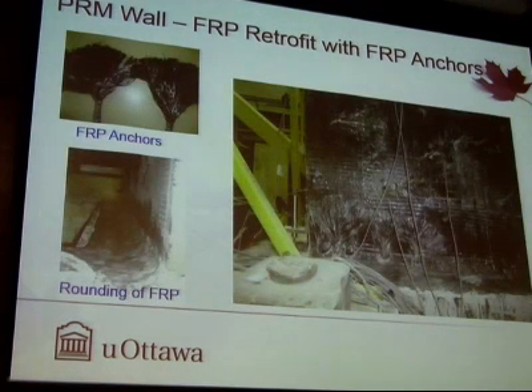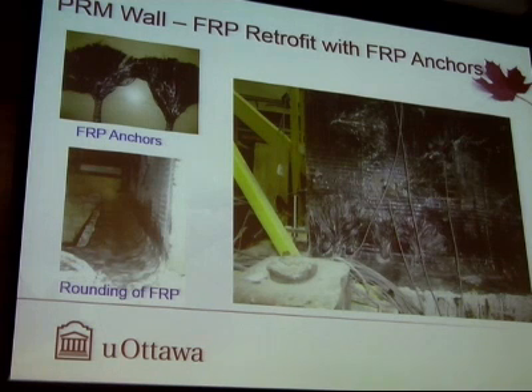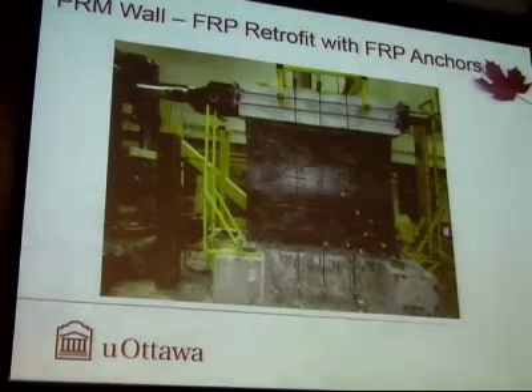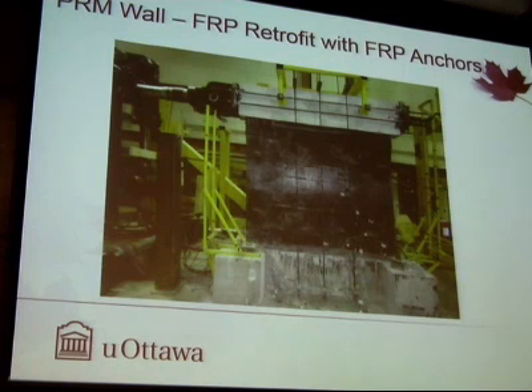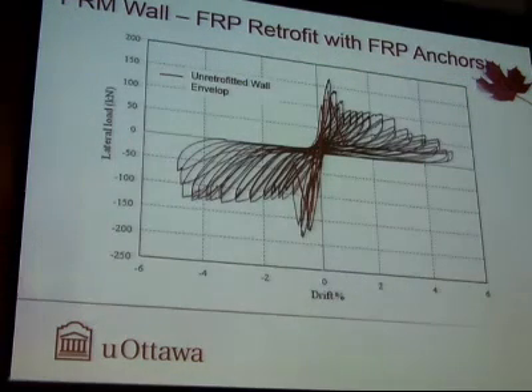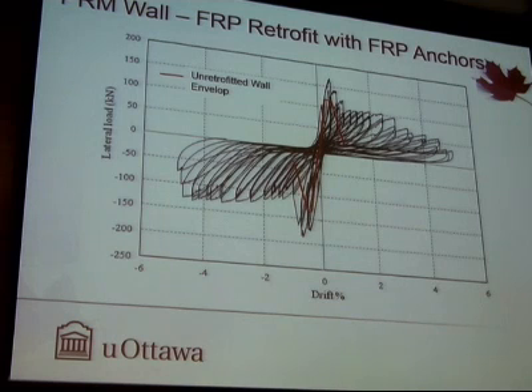The first application involved using anchors in a diagonal direction, provided with 30-degree inclination so that they would take tension in their longitudinal direction, as well as anchoring them in the foundation. We did get improvement. This is the wall test under reverse cyclic loading, but unfortunately the anchors were not placed right. The vertical anchors are supposed to be at least 2 inches or 50 millimeters, and they were short of that, and so the improvement in strength, flexural strength, was not as significant as we had hoped to attain, but